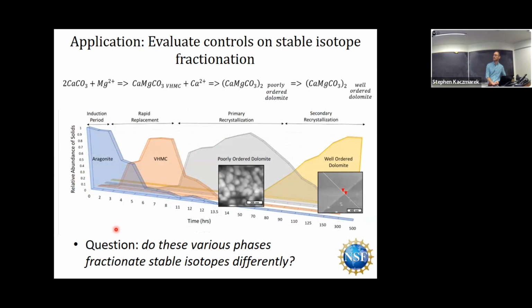What you've got here is a plot showing time and these are experimental results versus the relative abundance of the solids. In this set of experiments, we start with aragonite - you can see we start with 100% aragonite - and over the course of the first few hours that aragonite starts to dissolve.